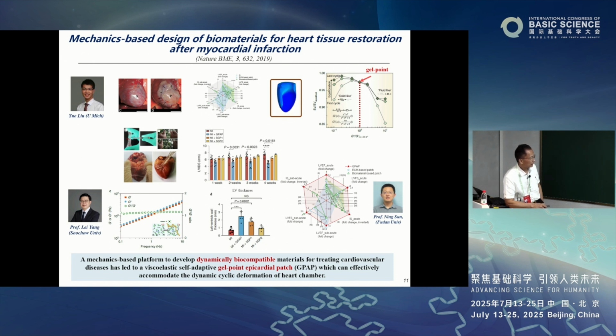So our collaborators, Professor Lei Yang from Soochow University, and cardiologist Professor Min Sun from Fudan University, have a test. Professor Lei made this gel-based material, with G double prime and G prime exactly the same across a wide range of frequency. The heartbeat is 1 hertz. This is the heartbeat. But this ratio is maintained equal to 1, and he was able to make this material over a wide range of frequencies.